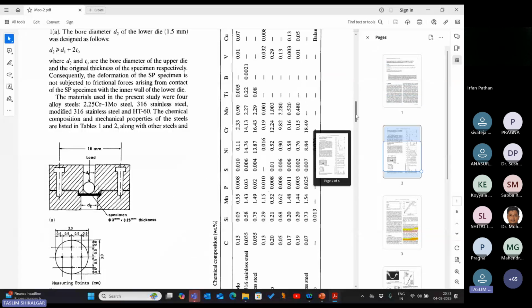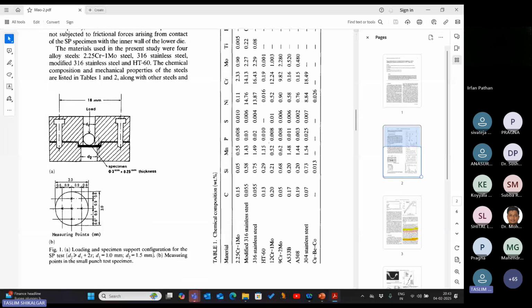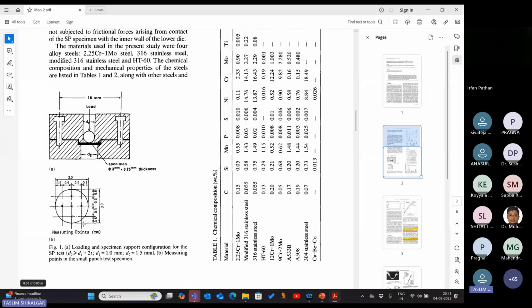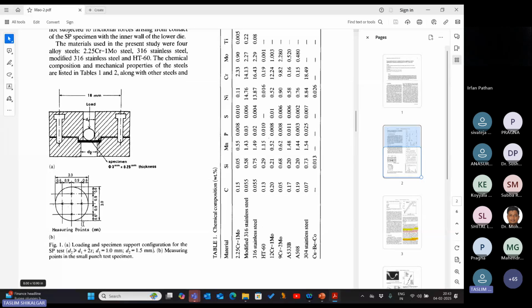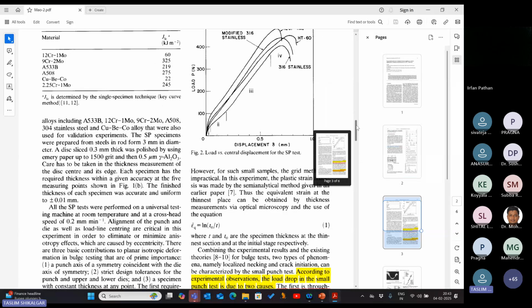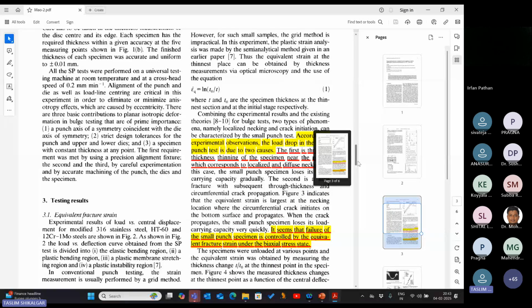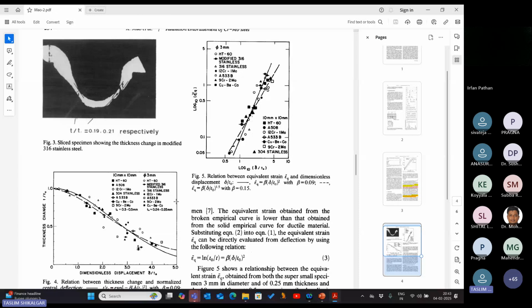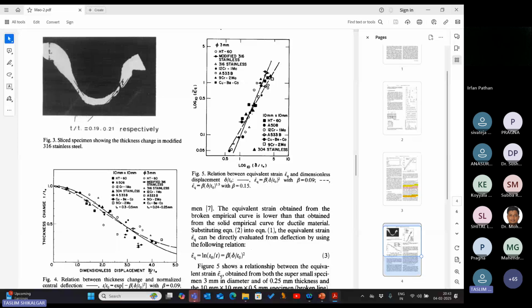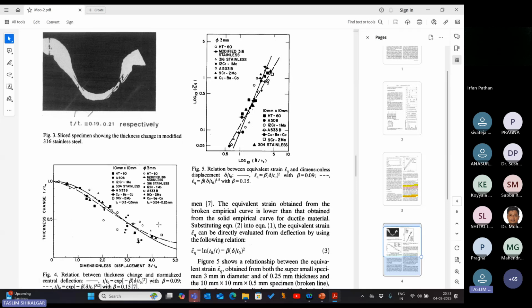Here also, he fabricated this type of fixture, very bold. He wanted to measure the dimensions of this type of specimen, but you cannot measure at a single location. So he measured at five locations, 1, 2, 3, 4, and took the average of these five locations, and that is the final dimension of the specimen. Here he tested multiple specimens, stainless steel 316, and found one non-dimensional number: the final thickness upon initial thickness, and the central deflection divided by T0. This is a useful methodology.